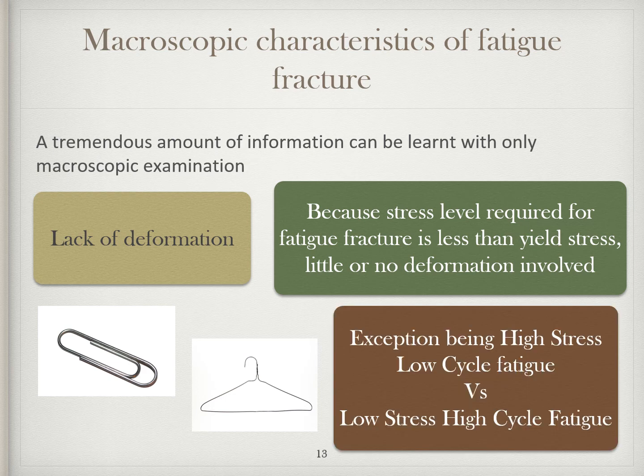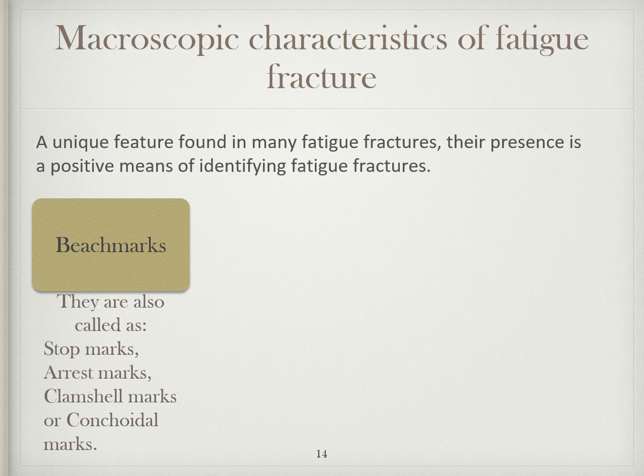Strictly speaking, this is fatigue because more than one stress application was required for fracture. However, this is not the typical fatigue fracture that occurs in most load-bearing parts, which have relatively low stress, high cycle loading. The second most important macroscopic feature of fatigue failure are the beach marks. Beach marks are a unique feature found in many fatigue fractures, and their presence is a positive means of identifying fatigue fractures. Beach marks also have been called stop marks, arrest marks, clamshell marks, and conchoidal marks, all in an attempt to describe their origin or characteristic appearance. The term beach marks is the most commonly used term.